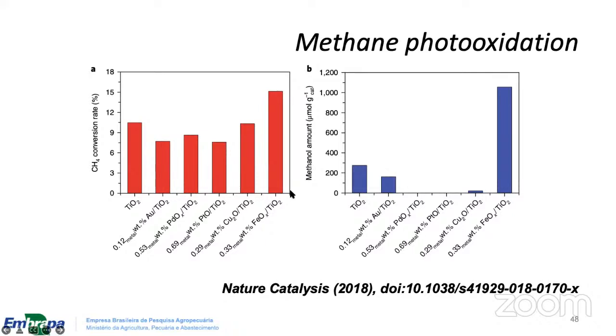methanol. You can see that the methane conversion rate that these authors got from pristine titanium oxide is not too different from the other systems. But on the other hand, the production of methanol is too low. This means that the system is going to the total oxidation of the methane to CO2 instead of oxidizing this in a controlled manner to methanol.